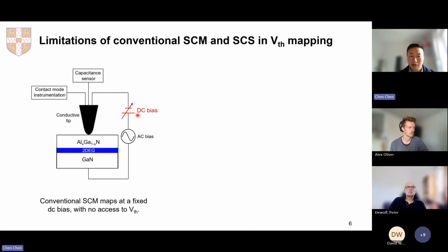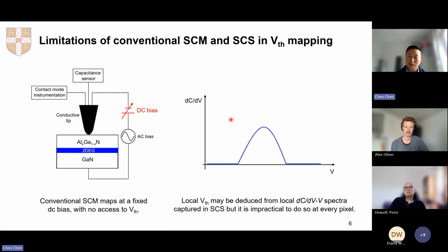So we need to add additional DC bias to deplete the 2DEG, and hence we can get conventional SCM signals. For this work, the task is more challenging: we not only want to get the SCM contrast, but also want to map the threshold voltage distribution. For conventional SCM itself, unfortunately, it only maps at a fixed DC bias, so there's no access to threshold voltage. In our SCS mode, yes, indeed, we can get a local dC divided by dV curve, and it's helpful to deduce a local threshold voltage value, but it's quite impractical to do so at every pixel.